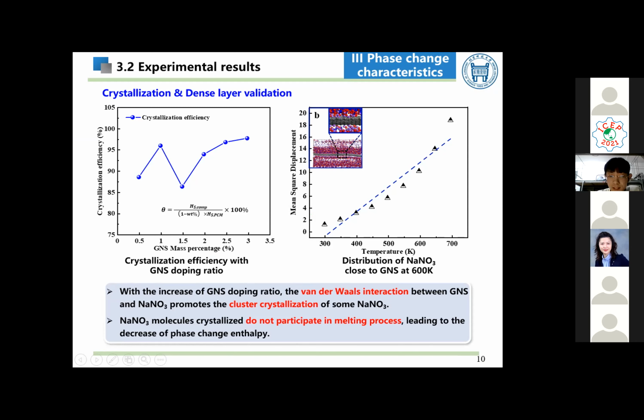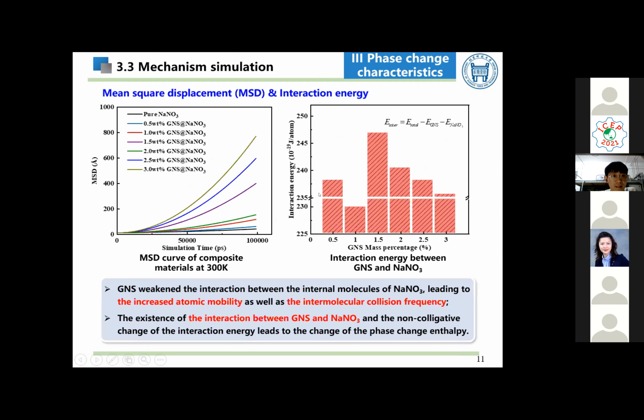We further observed the behavior of sodium nitrate close to GNS. It can be seen that the dense layer of sodium nitrate close to the nanosheet, and they do not participate in melting process. Mean square displacement can reflect the intensity of particle motion. It can be seen from the figure that MSD gradually increases at 300 Kelvin. We believed that GNS weakened the interaction between the internal molecules of sodium nitrate, leading to the increased atomic mobility as well as the intermolecular collision frequency. Thus, the melting point decreased.